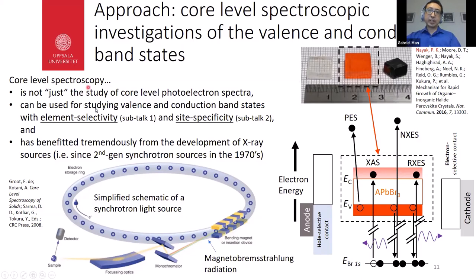The field as a whole has benefited tremendously from the development of X-ray sources, particularly in the 1970s with second generation synchrotron sources. So here's a simplified schematic of a storage ring minus the linear accelerator. And this is a simplified schematic of a beamline where there's an insertion device that generates magnetobremsstrahlung. The monochromator throws away some wavelengths and directs the rest to some focusing optics, which then focus the beam on the sample. And the detection is usually either electrons or photons are detected.